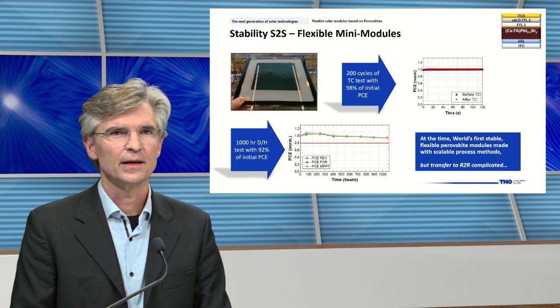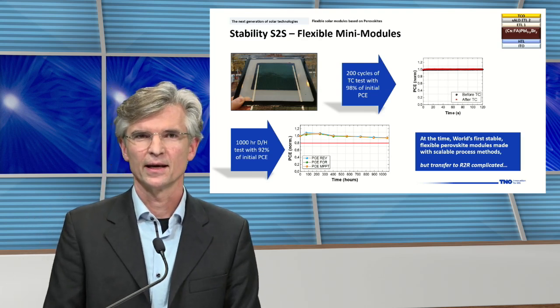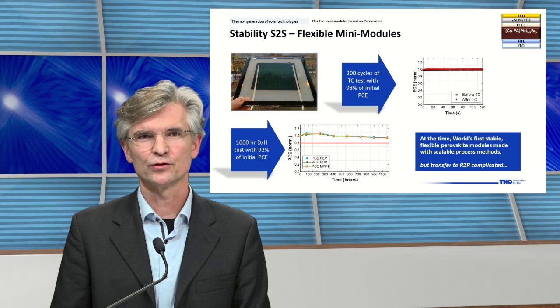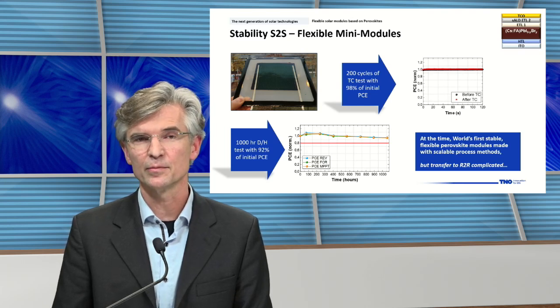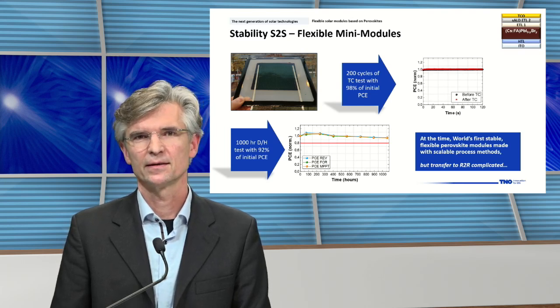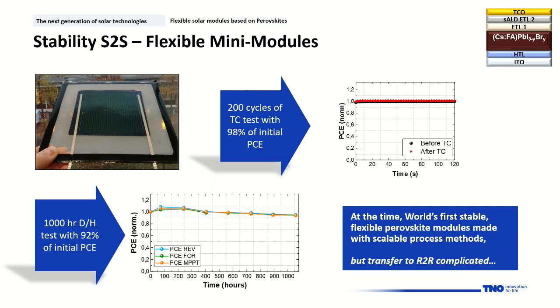Here we see the stability on flexible sheet-to-sheet processed mini modules. You see that after 200 cycles, you still obtain 98% of the performance. And after 1,000 hour damp heat, we have 92% of the performance left.